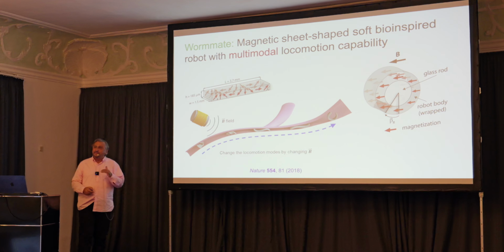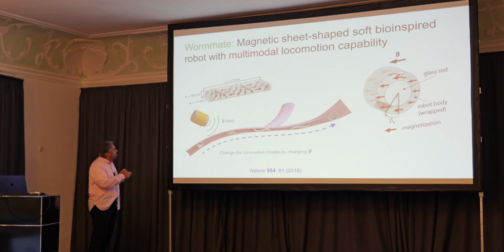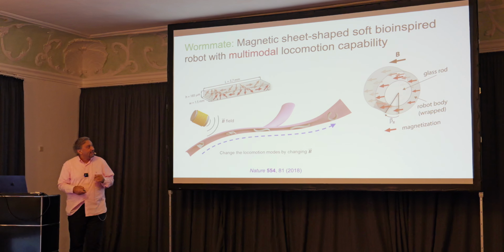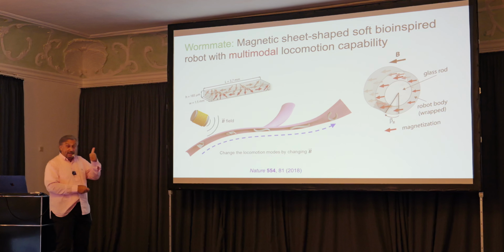We have seen waves are very interesting in physics, and here we figure out a waveform of magnetic profile, and amplitude is all constant in this case. It is a very interesting magnetic profile. Again, magnetic particles are here inside, so what we do is when the particles are non-magnetized, we wrap them around a cylinder, very simple fabrication, then magnetize it at a very high field, and then you can control the phase difference of the wave, so you can have one wave.